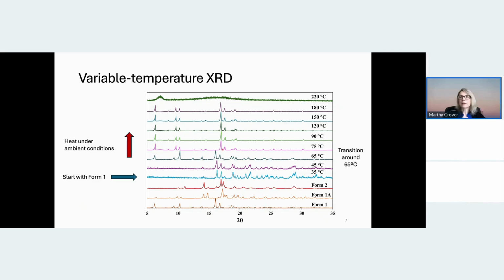And then by the time we get to 75, we have a structure that looks very similar to Form 1A. So it appears that under whatever the ambient humidity was, around 65 degrees C is when we had this transformation, again associated with water loss, presumably to form a structure that looks like the Form 1A structure that we saw dehydrated not in ambient conditions, but dry conditions. So again, these are all fairly consistent that the dehydration is occurring around 60 or 65 degrees, even in these very different environments.